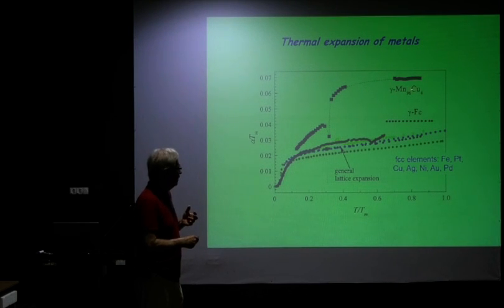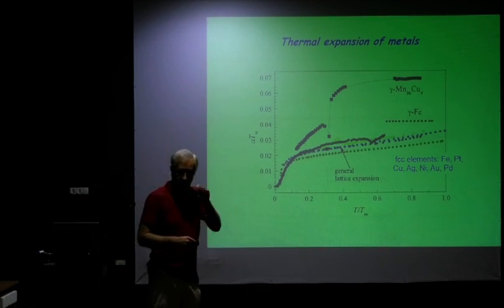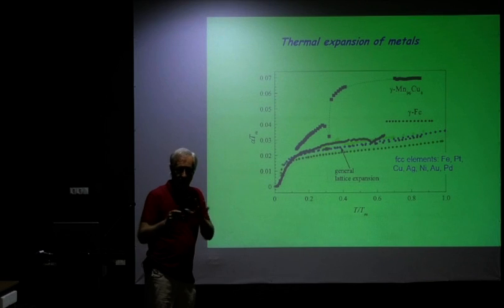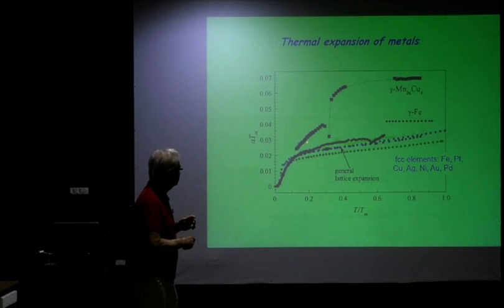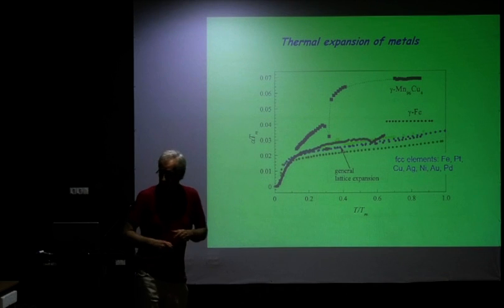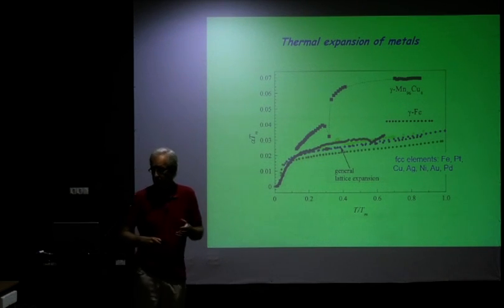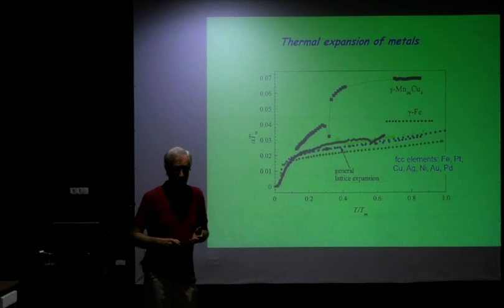And you get this value. This is gamma. If you put a little bit of copper into manganese, you can open up the FCC region so that you can stabilize the FCC state to quite low temperatures. So this would be the manganese copper that you have. This is more or less pure manganese, and this is all manganese copper, and this joins over here. This is basically then gamma manganese. So the question is now, what is going on?